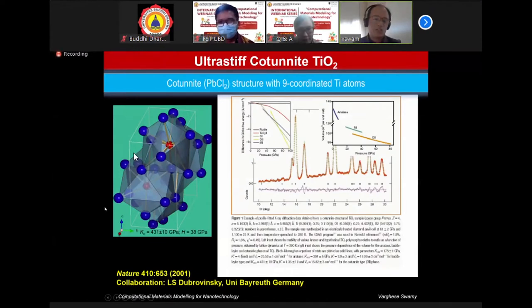And the cotunite structure, which I said we found, was actually a product of two approaches. One was the experimental approach together with first principles calculations. This was done in collaboration with people in Germany, and this was published a long time ago. The interesting thing is titanium exists in a particular coordination environment in relation to oxygen. Titanium is coordinated to 9 oxygen, and that was not known until that point, which means that it is highly packed. The polyhedra shown here are titanium-oxygen polyhedra, where each titanium atom is surrounded by 9 oxygen in the crystal structure.